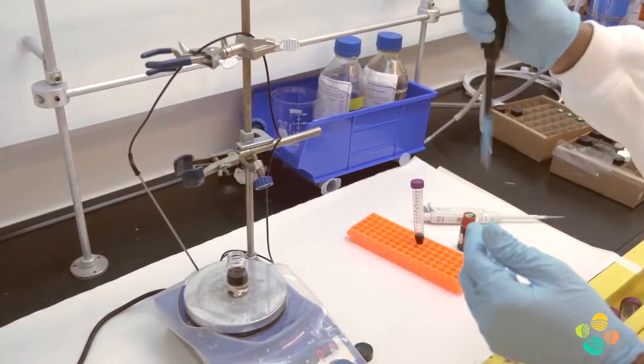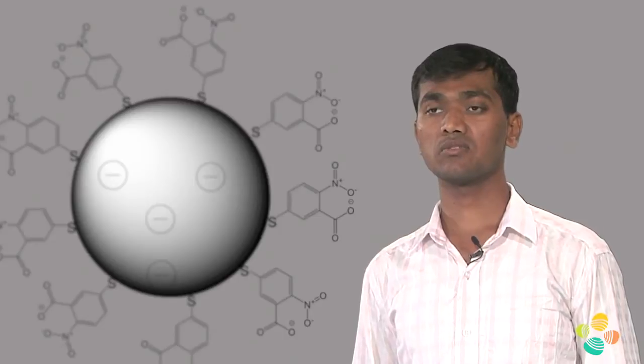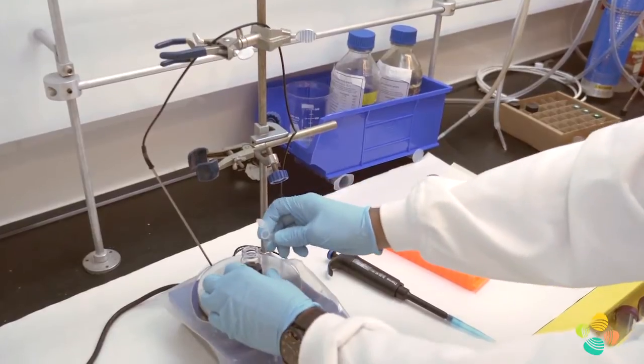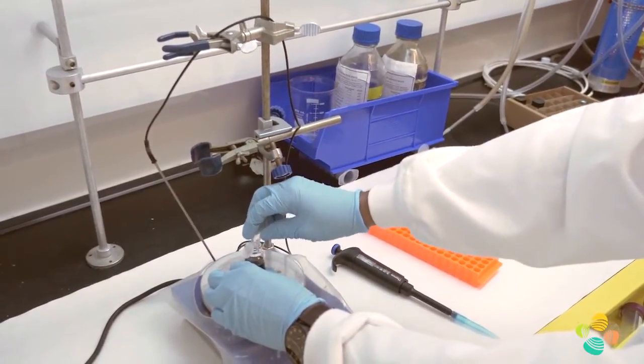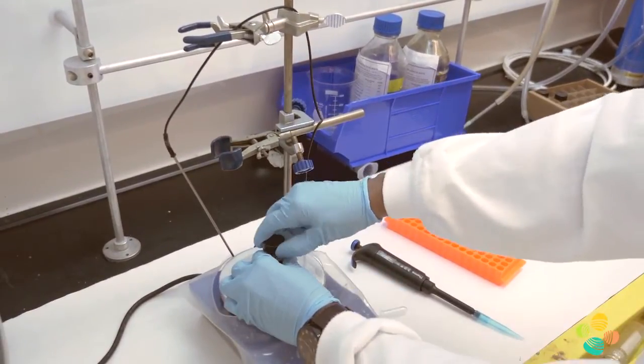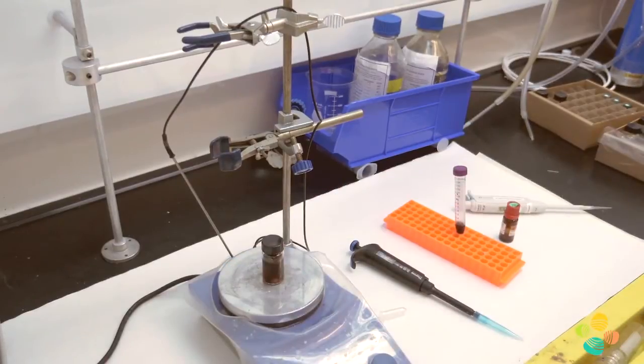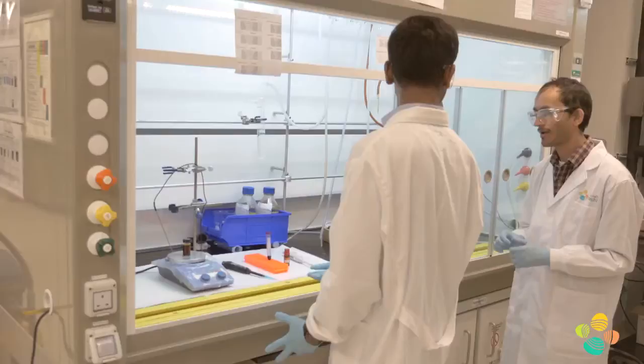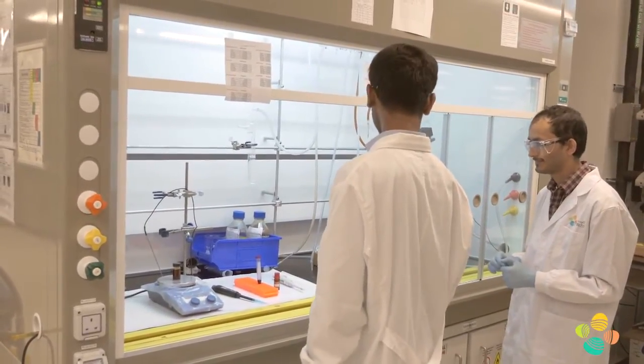Silver 35 cluster protected with glutathione ligands, which is water soluble, was transferred into dichloromethane phase which is organic using 4-fluorothiophenol. During this exchange we saw the cluster core change from 35 to 44. This cluster change in properties as well as size were characterized using mass spectrometry.